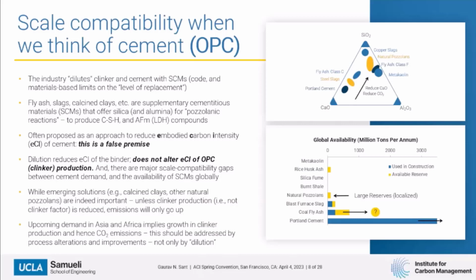Here's the reason why. You're not changing the carbon intensity of producing the clinker. You're diluting the clinker with something else. And there's a big difference in these two things. So on a per unit basis, you're definitely reducing the carbon intensity of the binder, but you're not changing the carbon intensity of cement production itself. So dilution definitely reduces ECI, right? So no question about that.